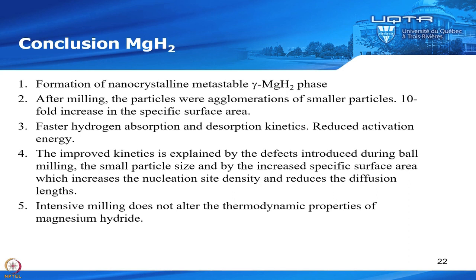But we also saw that intensive milling does not alter the thermodynamic properties of magnesium hydride. And this is a common feature in nanocrystalline materials. Usually you do not change the thermodynamics unless you go to very, very small crystallite size. So for example, for magnesium hydride, the thermodynamics starts to change at about 7 nanometers, and just a little bit. In order to have a good change of thermodynamics, you have to reach like 2 or 3 nanometers, and this is not the type of size that we get by ball milling usually. So it's much too small. So in principle, by ball milling usually you do not change the thermodynamics.